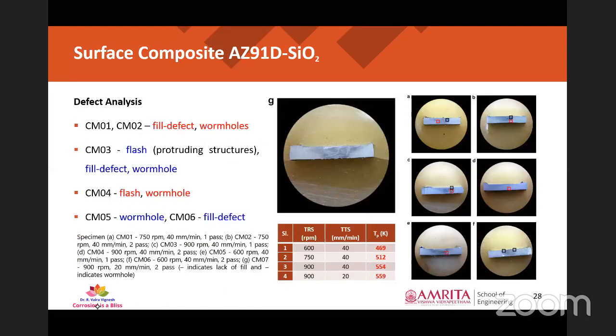So here we have done around 8 experiments to optimize the parameters. One is the tool rotation speed, and second is the tool traverse speed. So specimen A, which is shown over here, which is CM01, it was processed at process parameters of 750 rpm and 40 mm per minute for a single pass. In that, we have observed fill defects and wormholes too. In case of specimen 03, we have observed flash and fill defect and wormholes in the material. You can observe all these defect features in the macro structure that is given over here.